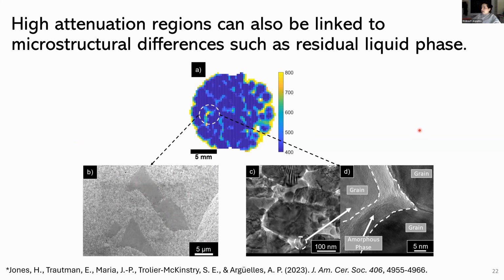And then the other part that we were able to observe is that for the zinc acetate samples, and this supports the argument about a weaker bond between the grains, there was actually some residual liquid phase, so that zinc acetate wasn't fully leaving the system during the sintering process. And again, although we are by no means suggesting that we're able to image things in the 5 nanometer or 100 nanometer range, these measurements allowed us to target specific regions to study further and understand through the use of microscopy exactly what might be happening in those regions.